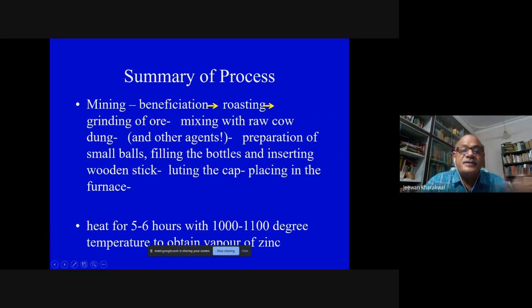So the summary of this entire process: mining was done, then beneficiation of the ore, roasting, and grinding of the ore, then mixing it with raw cowdung. Sometimes other agents may also have been mixed, as the literature says. Then came preparation of small balls, filling in the bottle, inserting the wooden stick, luting the cap and placing it in the furnace. Heat was given for 5 to 6 hours, at a temperature of 1000 to 1100 degrees.